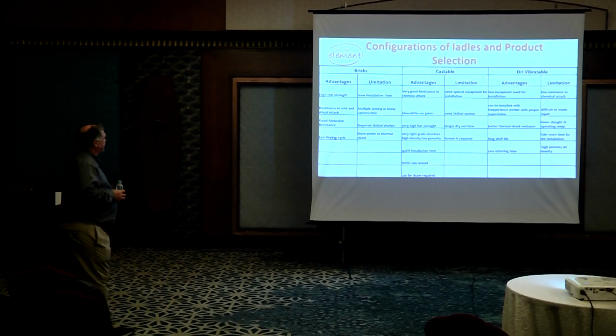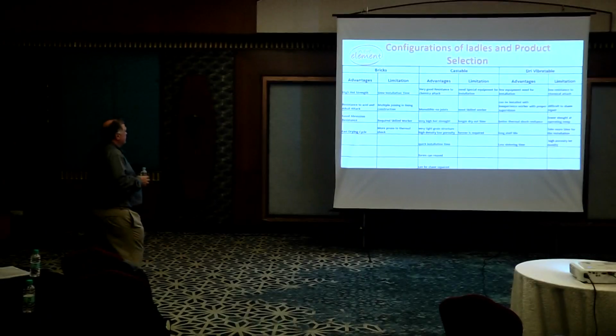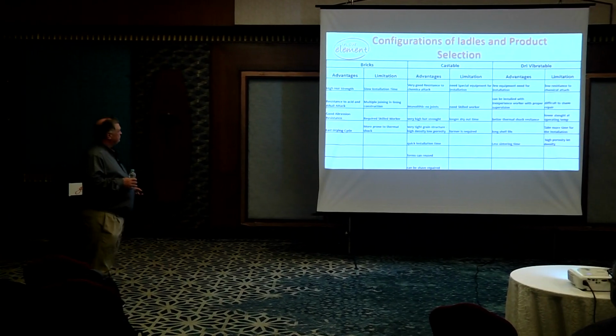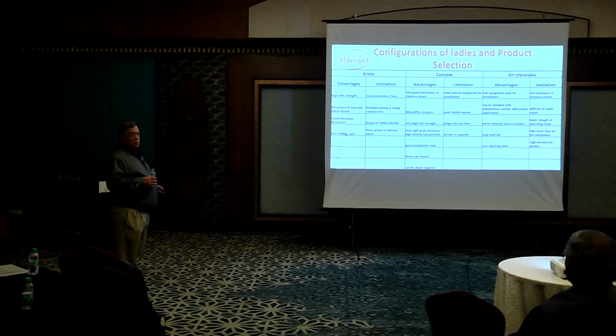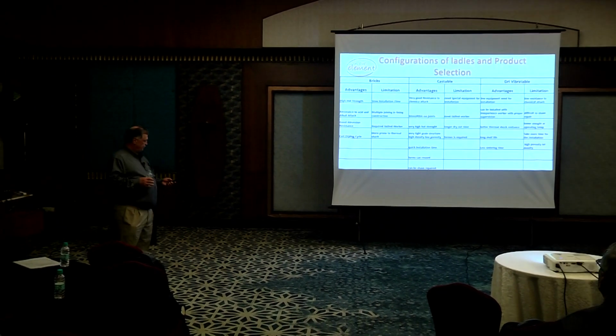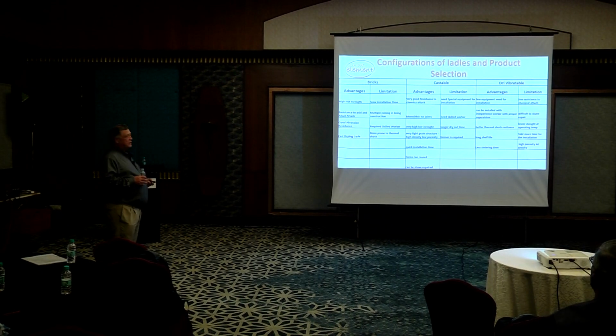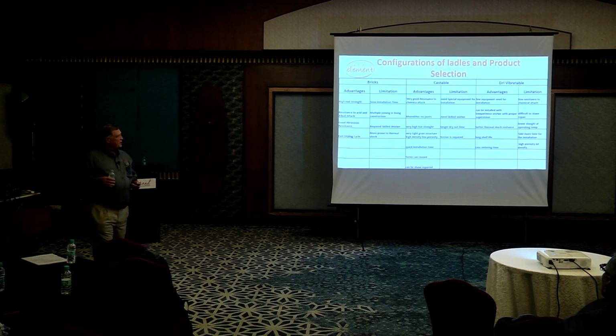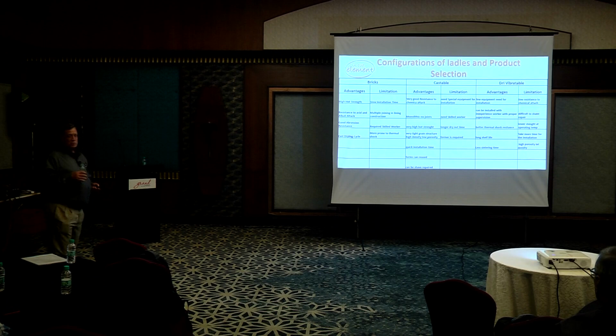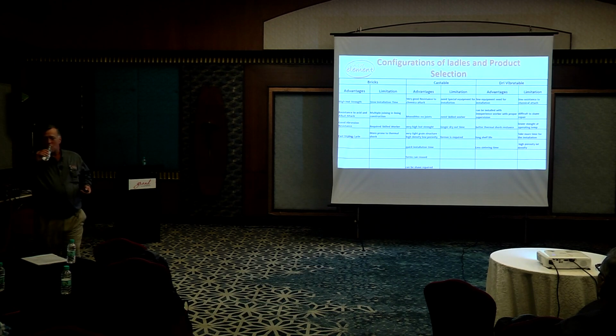The advantages of bricks are good high hot strength, resistance to acid and alkali attack, good abrasion resistance, and of course fast drying because they're already dried. Disadvantages: slow installation time, lots of joints. I mean, basically you're building a lining with cracking. Skilled workers are hard to find for laying brick, and bricks are more prone to thermal shock. If you thermal shock a brick, you're creating hundreds, maybe thousands of cracks because of the mortar joints.